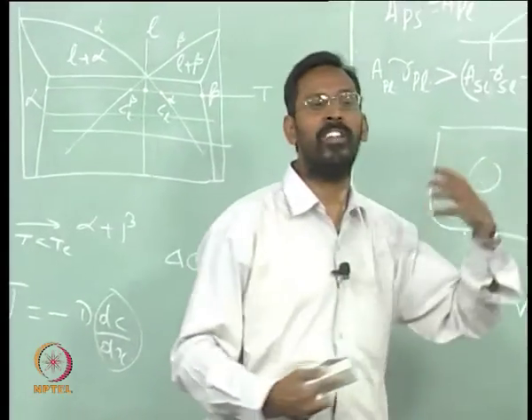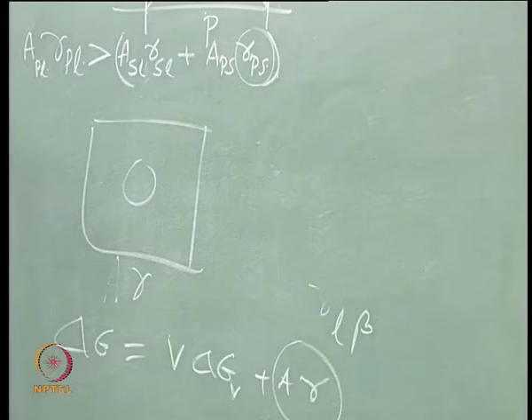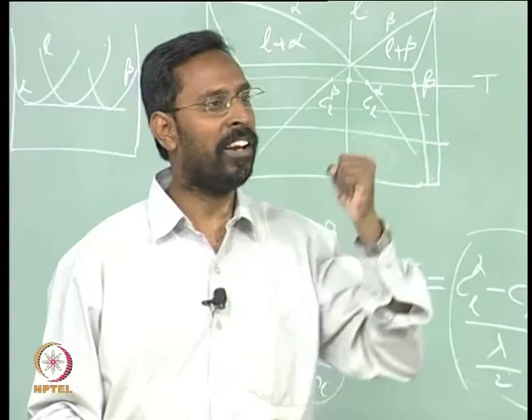Similarly, silicon has nucleated first compared to alpha aluminum. By looking at the microstructure, we can know which phase nucleated first, and that gives an idea about interfacial energy. But interfacial energy is just one aspect.